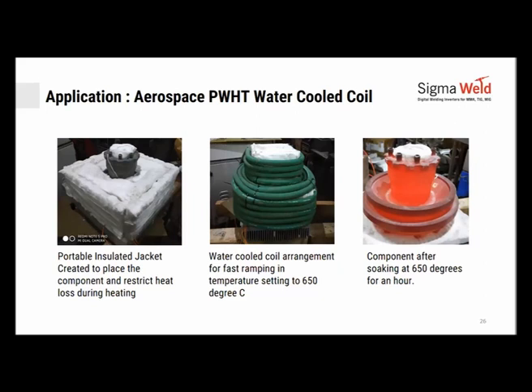The way to do this was in two shifts, two parts. So we built a portable oven around the job itself. We wound the water cooled coil and preheat it up to 650 degrees and hold it there for an hour. Entire job is at 650. This job is then immersed into an existing furnace, which is already fired up at about 1100 degrees. That's the only way to achieve this solution. Otherwise, it's not possible. And this was really a tricky part to achieve the desired results here.